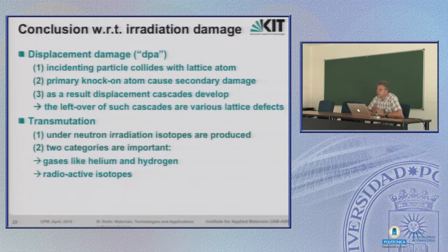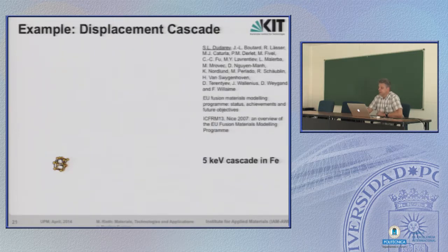As a conclusion, displacement damage we measure with dpa units. An incident particle collides with a lattice atom. This produces a primary knock-on atom, which causes secondary damage. And as a result, displacement cascades develop. And the leftovers of such cascades are various lattice defects, as we will see in the next chapter. Then the second kind of damage, that's transmutation. Under neutron irradiation, isotopes are produced. Two categories. One is gases like helium and hydrogen. The other ones are radioactive isotopes. This is irradiation damage, and we will see the consequences.